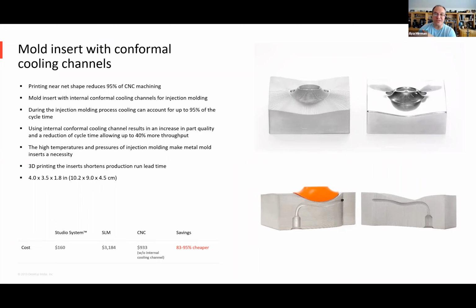The second one, of course, is the ability to create a geometry that you can't produce any other way, which is an internal cooling channel. And so here's an example of that. Basically, the closer you can get the cooling channel to the part, the faster you can cool the part down and increase the cycle time. And typically that can increase things 25, 40%, which is a big deal for relatively low margin kind of operations.